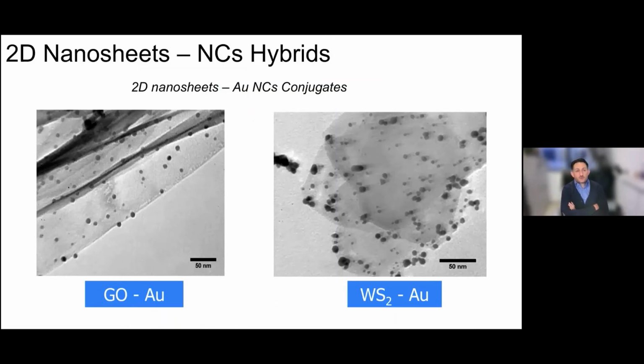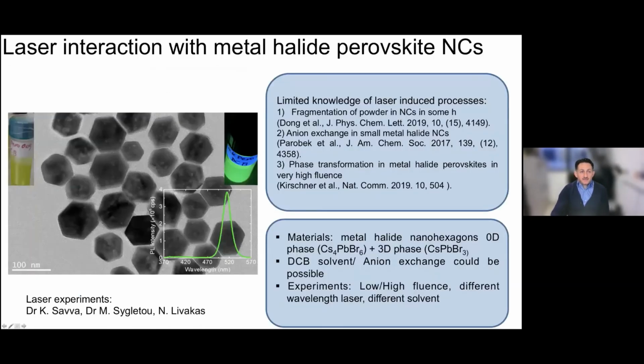These are our old results related to conjugation of gold nanocrystals on two-dimensional nanosheets. This is the case of immobilization of gold nanoparticles on graphene oxide, and this is the case of tungsten disulfide. But then we have applied this on metal halide perovskite nanocrystals. That is actually an unexplored area. There is limited knowledge, but there are some works related to fragmentation of powder, anion exchange, and phase transformation. And these are the materials that have been used to date.